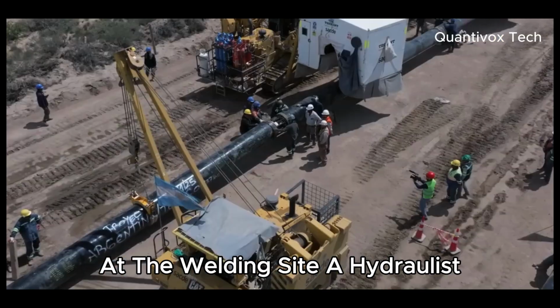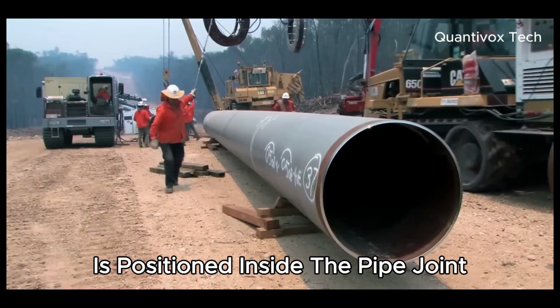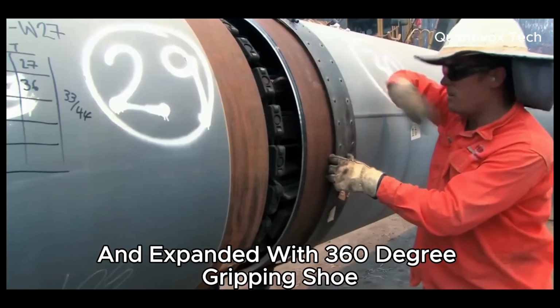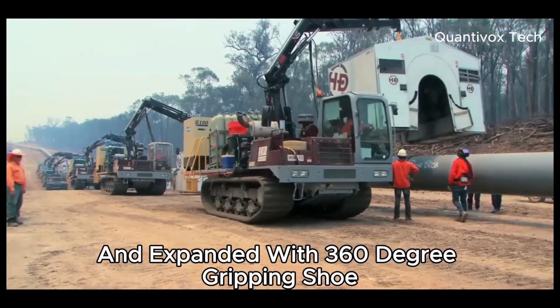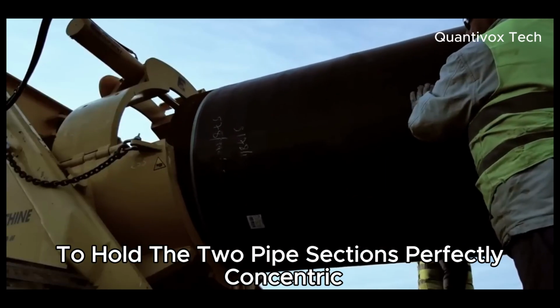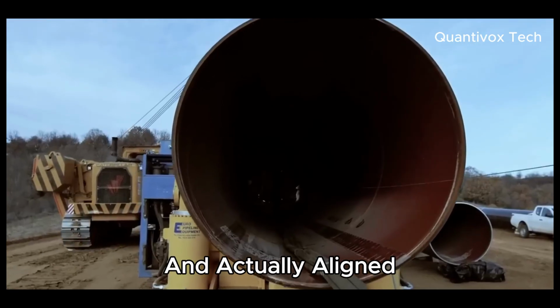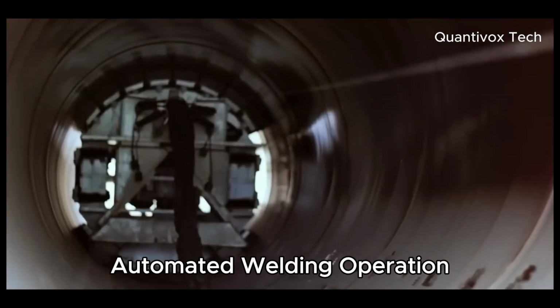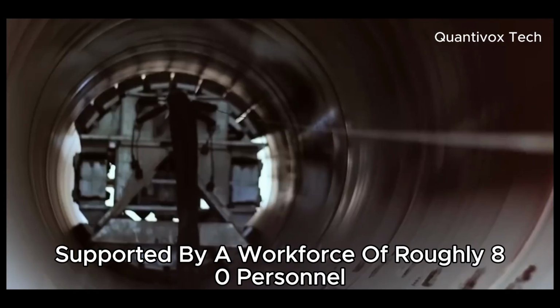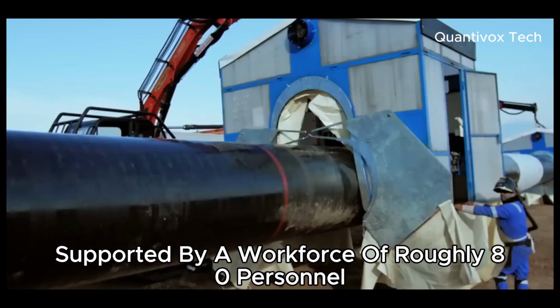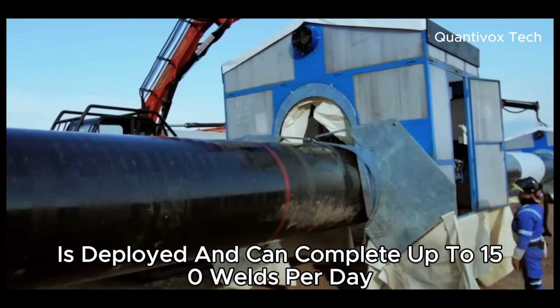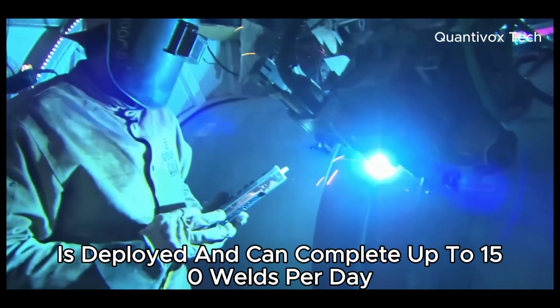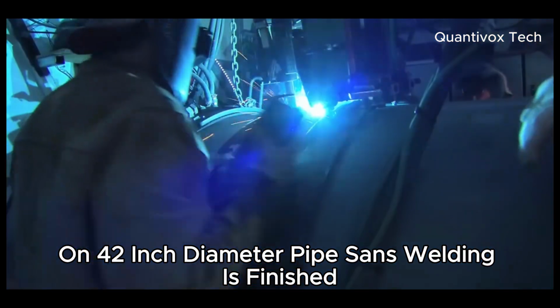At the welding site, a hydraulic internal line-up clamp is positioned inside the pipe joint and expanded with 360-degree gripping shoes to hold the two pipe sections perfectly concentric and axially aligned before and during the root pass. An automated welding operation, supported by a workforce of roughly 80 personnel and dozens of specialized machines, is deployed and can complete up to 150 welds per day on 42-inch diameter pipe.